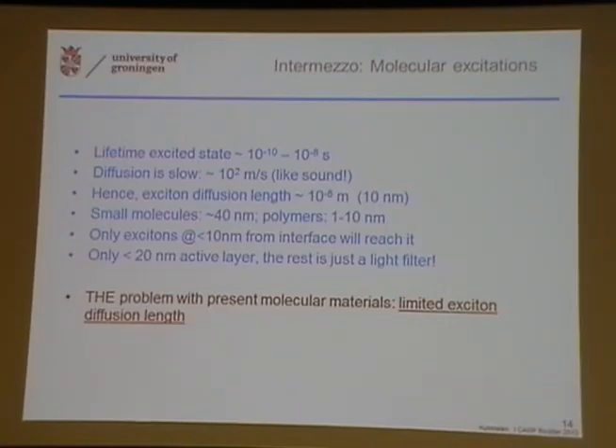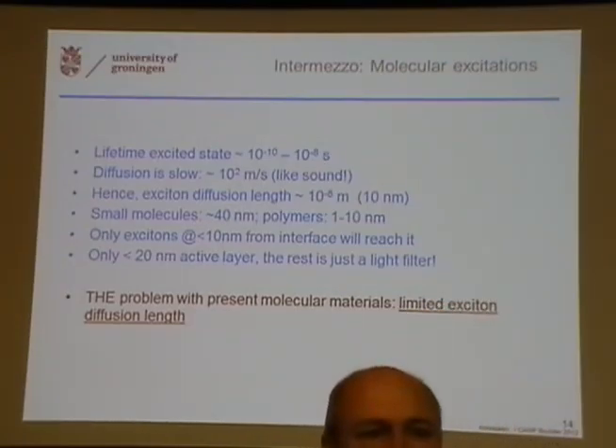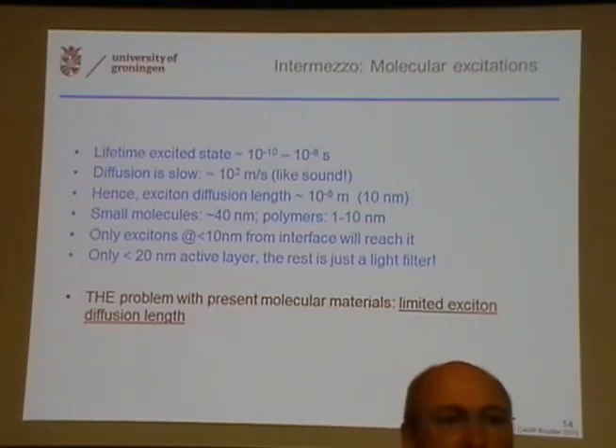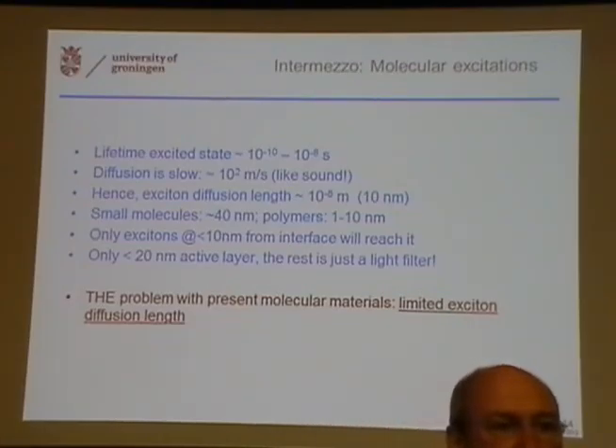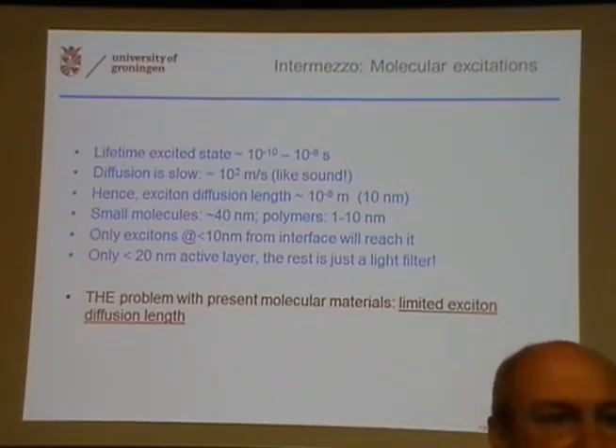If you want to have an efficiency of, let's say, 99%, you better do this within 10 picoseconds, 100 times faster. Yeah, something like that. That's a rule of thumb you can think. But diffusion is extremely slow. I didn't know, but apparently that's something like the speed of sound, which is disappointingly slow for me. But that's the way it is.